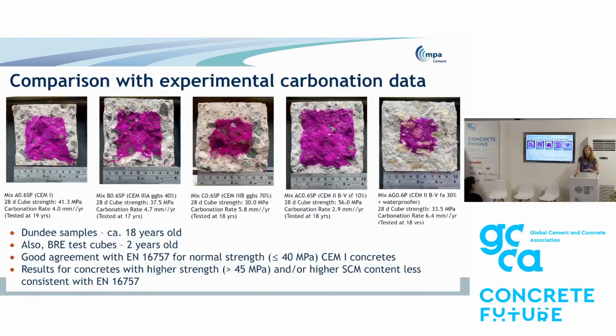And we're quite lucky in the UK. Dundee University has samples at 18 years old, so they've been curing for a little while. And the Building Research Establishment has some that are 2 years old. And we were able to test these to check what the carbonation is. And what we found was that for normal strength concrete, so less than or equal to 40 megapascals, there was very good agreement between the methodology in the EN 16757 and the cubes that we tested.